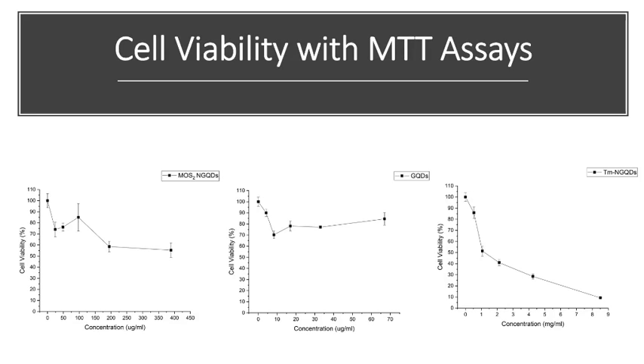We had to add a surfactant to it, which makes it much more toxic to the cells, in order to break down that molybdenum disulfide. So we actually had to do another set of serial dilutions on the molybdenum disulfide to see any viability. It has a much smaller concentration than the other 2 samples. Serial dilutions are also done with DMEM, that medium again.